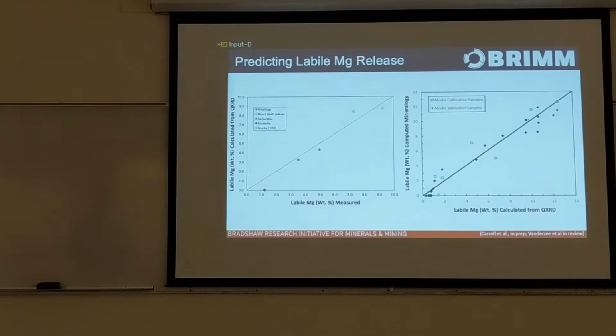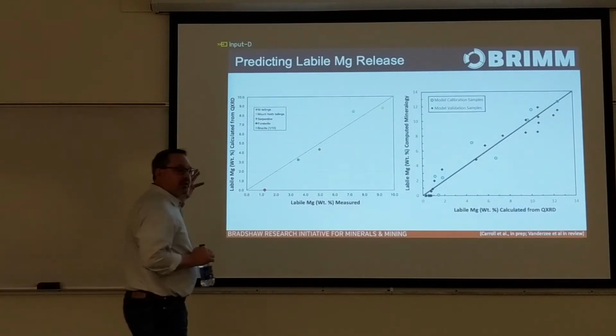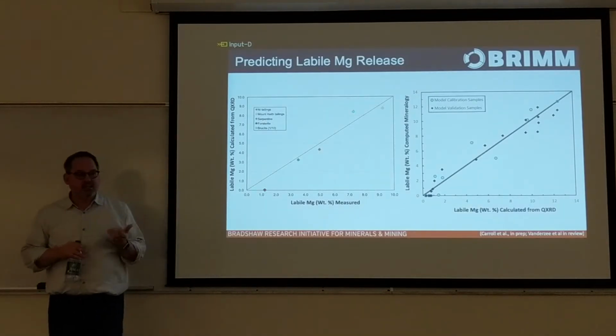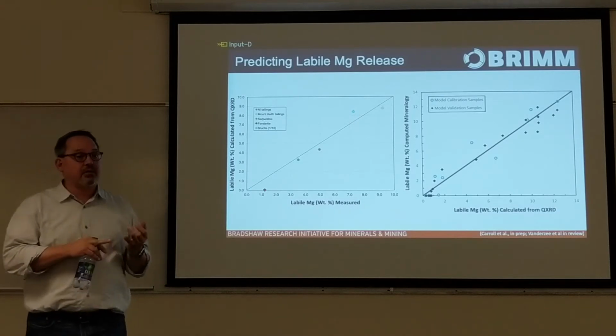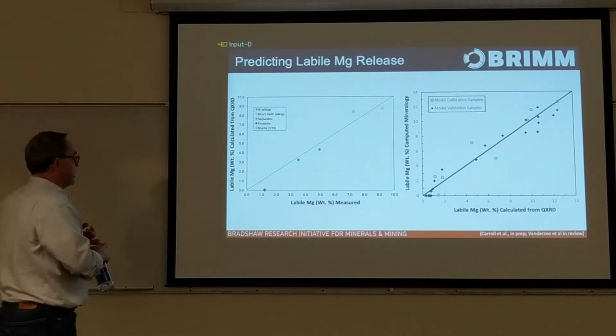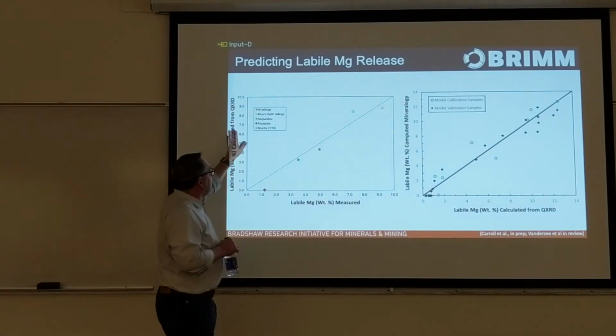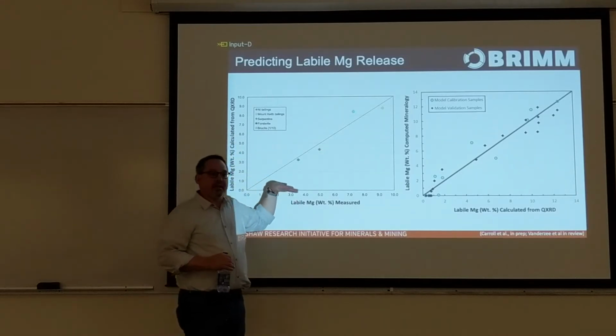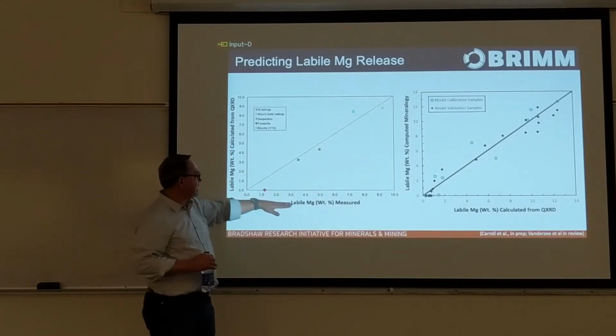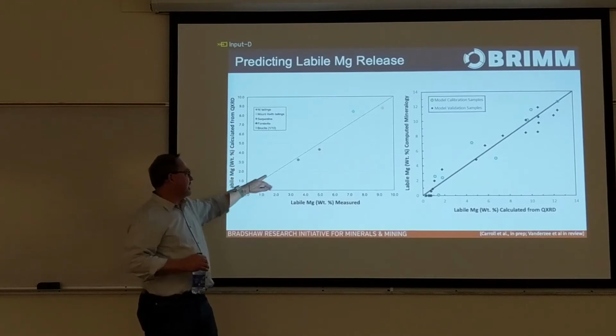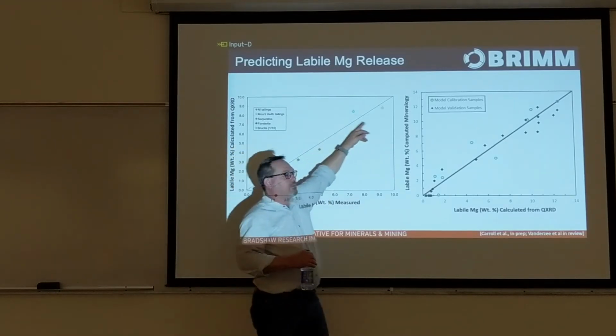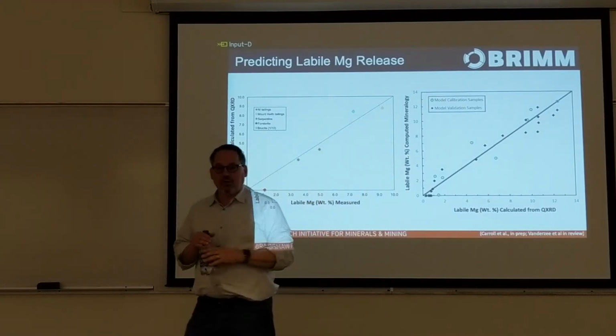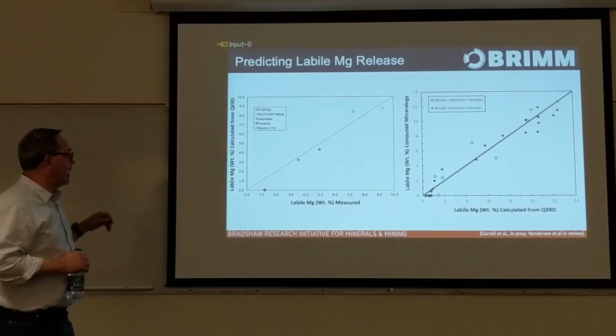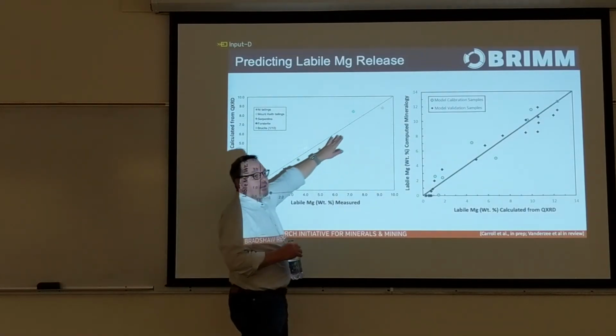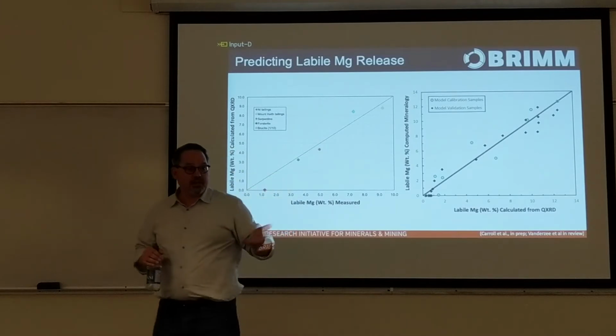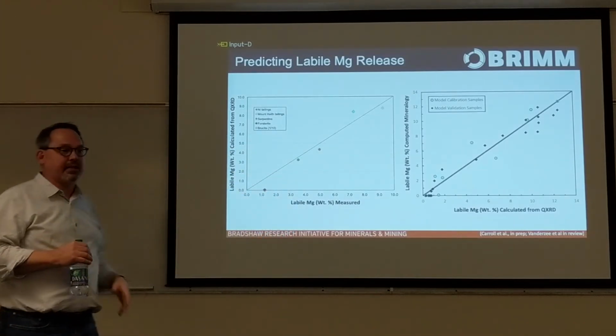But we have a mineralogical understanding of what imparts this labile magnesium. It's mineral abundance, especially trace minerals, and surface reactivity and surface area. So this is an example where we've adopted that assumption, made some chemical and physical measurements on tailings, and actually calculated the labile magnesium versus the labile magnesium content measured in that flow-through reactor. And you can see for a first-order cut, by knowing the mineralogy of the material and the surface area and things like that, we can calculate labile magnesium reasonably accurately.